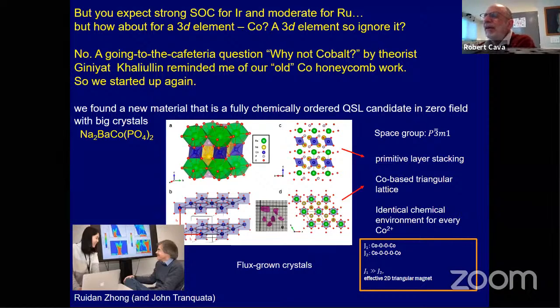So the problem with a lot of these oxides is that when you couple the transition metals too strongly, then they will magnetically order at some high temperature. No matter what, they'll find some dominant magnetic interaction, and they'll do something you don't want them to do. But luckily, these are far enough apart that they don't couple directly, and then you can get some kind of unusual magnetic state, and you can grow large crystals of these things from a flux.